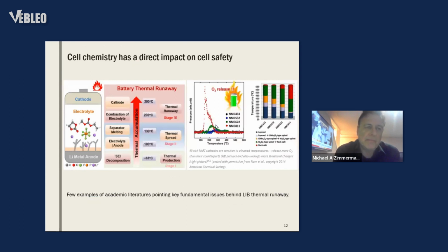The cell chemistries have direct impact on this thermal runaway problem. Typically what happens is that you have some decomposition in things like something called a solid electrolyte interface layer. It generates heat, and then the electrolyte and the anode itself heat up, and it can run up to 100 degrees centigrade. The temperature goes higher, the separator starts to melt, and at about 200 degrees centigrade, you can have combustion, and the cathode drives further thermal runaway. On the right-hand side of this slide is one of the fuels for this fire, which is certain gases plus oxygen that get emitted from the cathode material, and that becomes the fuel to cause a fire. The chemical composition of the electrodes is basically what causes combustion and thermal runaway.